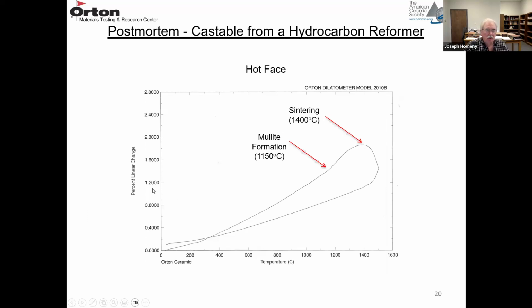So I put this on here. This is a thermal expansion trace. So when you're doing a failure analysis, there's other things you can do besides looking at the microstructure with an SEM, trying to figure out what happened to the chemistry. We showed some X-ray diffraction work, so you can see what happens to the phases. But this is an example of how to use a thermal expansion to see what might be the highest use temperature that this refractory saw during service. So a lot of times a failure analysis involves overheating a furnace. So this is useful for a castable only.